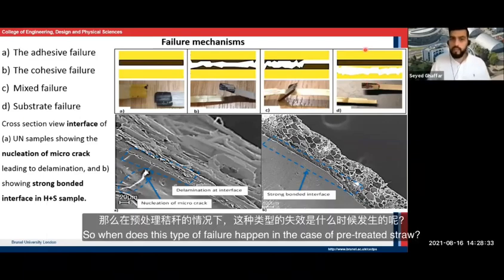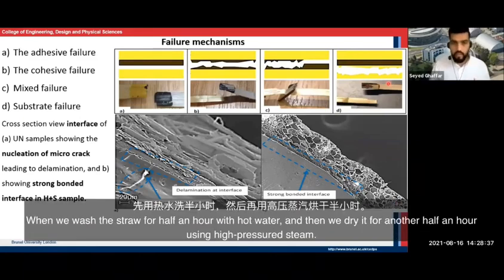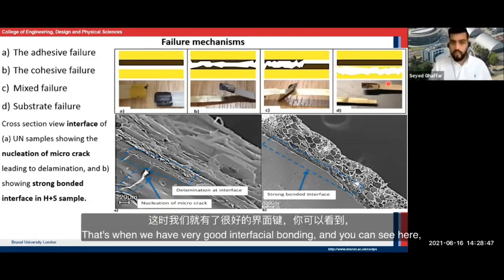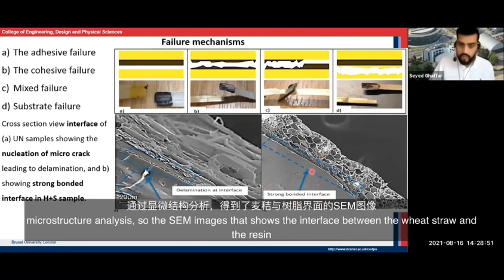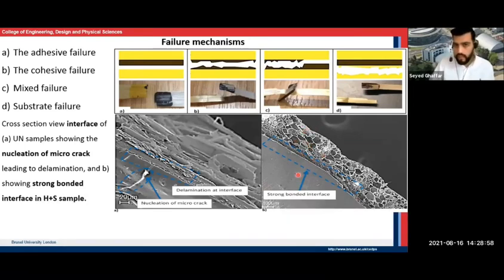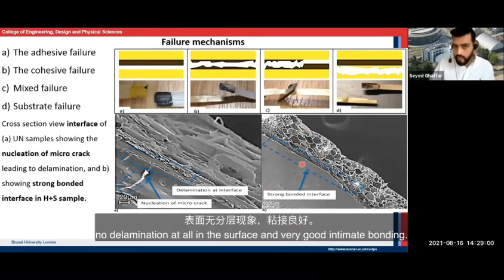So when does this type of failure happen? In the case of pre-treated straw. When we wash the straw for half an hour with hot water and then we dry it for another half an hour using high pressure steam, that's when we have very good interfacial bonding. And you can see here the microstructure analysis, the SEM images, which show the interface between the wheat straw and the resin. No delamination at all on the surface and very good intimate bonding.